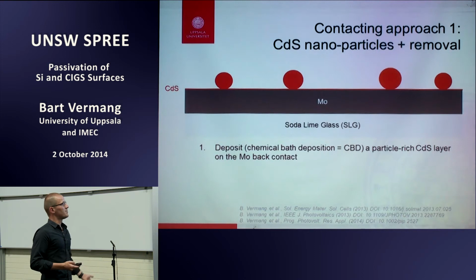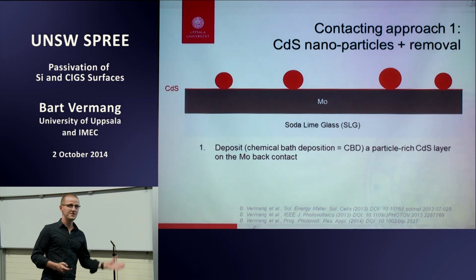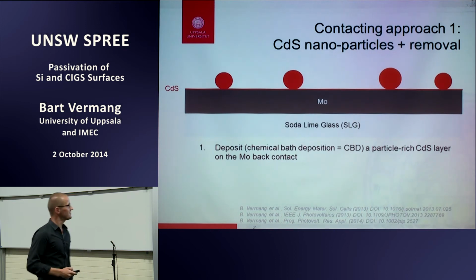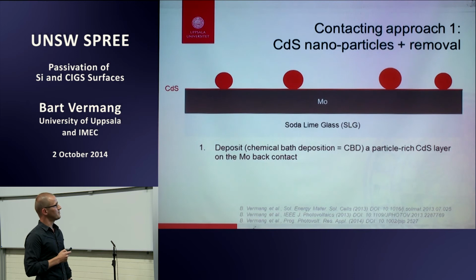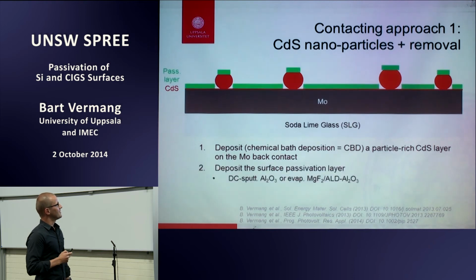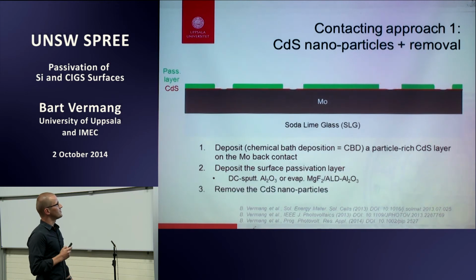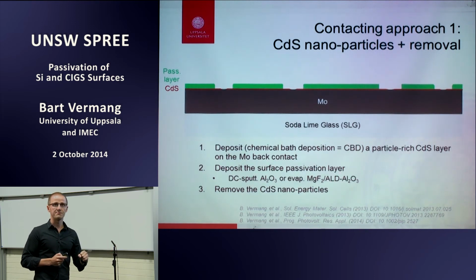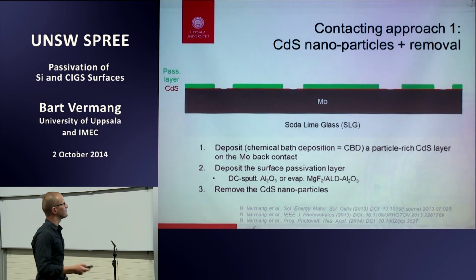The normal chemical bath deposition we use for making the buffer layers has one disadvantage. It makes nanoparticles in the bulk, and they are deposited, but we use them to our advantage. So if you first deposit cadmium sulfide nanoparticles on the molybdenum rear contact, then sputter or evaporate a passivation layer and remove the nanoparticles afterwards, you can make nice openings in the passivation layer, especially in the case of aluminum oxide, which is very strong, so you're not going to scratch it or whatever.